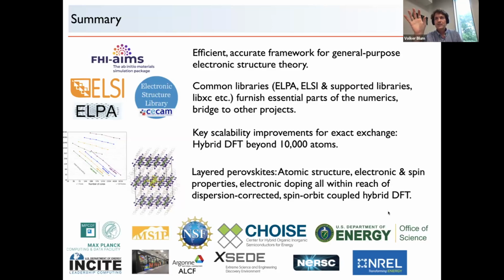The structure usually starts at the X-ray structure, but we get certain aspects better than the X-ray diffraction, for example, hydrogen bonds. So the DFT will actually correct artifacts of the X-ray structures for hydrogen bonds. And that's why we do this. And so for the structure optimization, absolutely we need a good density functional, and we use a Tkatchenko-Scheffler correction in this case. But we could do better, and the reason we use PBE plus TS is because it's the most affordable method that we have, and it's worked for us for many years, but there's no problem doing more.